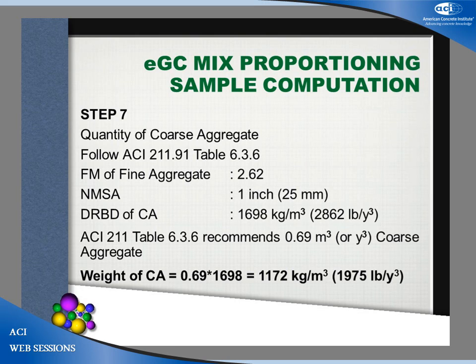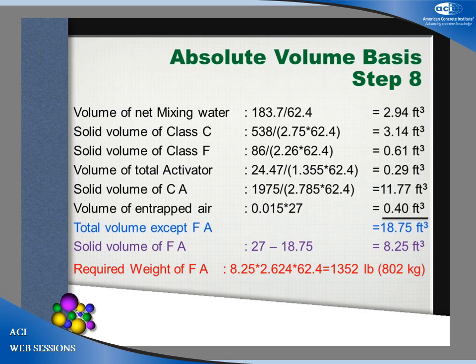We know our dry rodded bulk density of coarse aggregate is 1698 kg per cubic meter, so we multiply with the 0.69, that gives 1172 kg per cubic meter or 1975 pounds per cubic yard. So we got the coarse aggregate quantity as well. Now step number 8,